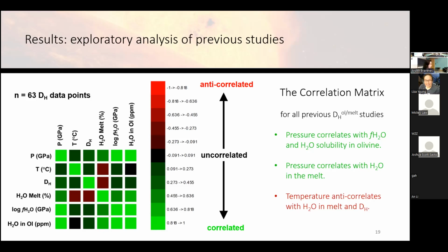But you'll also notice that pressure is going to correlate with fugacity, and it also correlates with solubility of hydrogen in olivine. Pressure also weakly correlates with the water contents of the melt. And there's an anti-correlation with water in the melt and the partition coefficient.